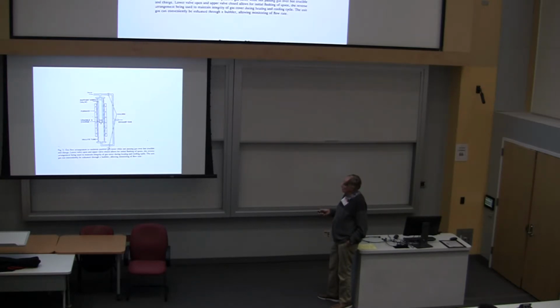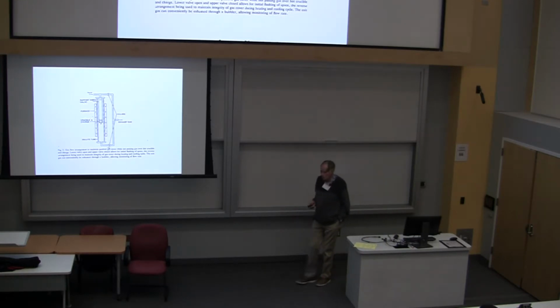So then, as I say, you go up to 1500, soak it, cool it down. Typical ramp speeds anywhere from a few degrees an hour to 10 or 15 degrees an hour, depending on what you're trying to do, and then leaching it out in the end. And these days, there's always this particular problem of getting rid of the leaching solution when you're done, which is a chemical waste problem. It's its own business.